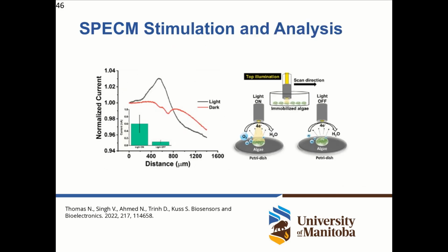So then in our SPECM stimulation experiment, we are scanning across single cells of algae and record the current while either switching the light on or off at our electrode. So first have a look at the red curve here, where you see a decrease in current when the electrode scans over these cells. And this is a big contrast to when we switch the light on and we perform these scans across cells, where you see a pronounced peak. I have to correct myself here a little bit because we are performing oxygen reduction at the electrode, but the cells are producing oxygen. And so we can also quantify this current that is shown there in the inset, which is statistically significant.